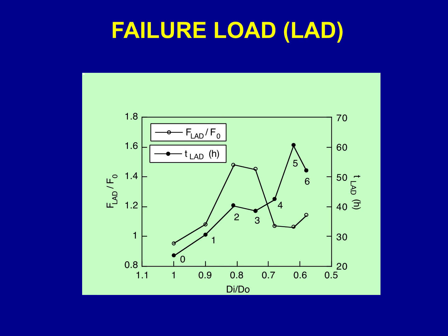The vertical axis on the right hand side represents the time to failure under localized anodic dissolution, LAD, or stress corrosion cracking conditions, and the horizontal axis represents the cold drawing degree through the ratio from the diameter at any step of drawing, di, divided by d0, the initial diameter before cold drawing.